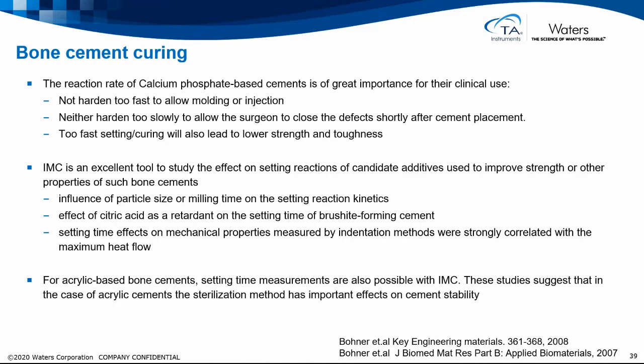Microcalorimetry is an excellent tool to study the effects of the setting reaction, and you can test with different additives to improve strength or other properties of the bone cement. There are examples of looking at influence of particle size or milling times on the setting reaction kinetics, effects of adding citric acid as a retardant on the setting time. The setting time effects on the mechanical properties are measured by indentation methods, and they are strongly correlated with the maximum heat flow. So calorimetry and mechanical properties are related.